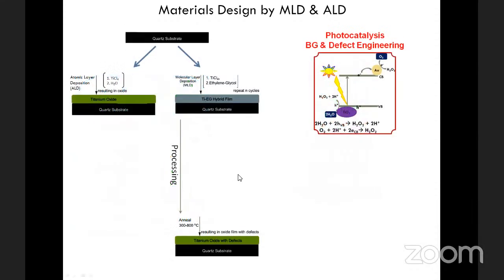So the idea was, when we started this journey quite a bit long ago, to take some substrate and deposit titanium dioxide on the substrate and then study the photocatalysis of these thin films. One may go with the approach of using atomic layer deposition using titanium tetrachloride and water and directly deposit titanium dioxide and study its properties. However, we decided to do the following thing.